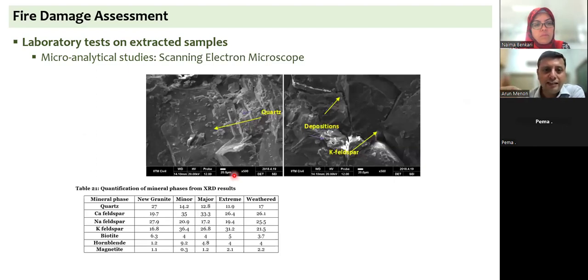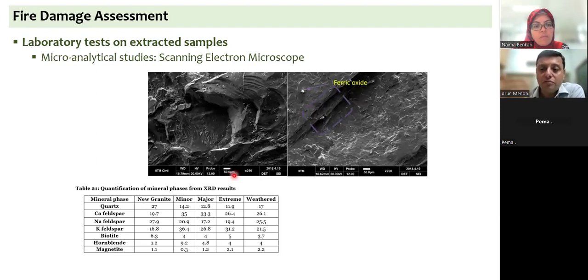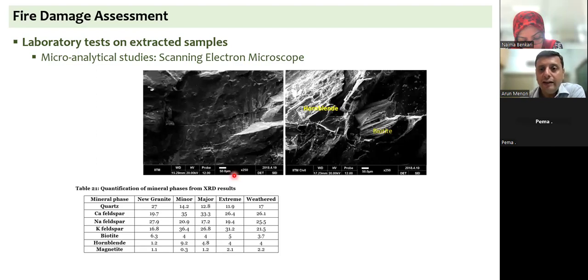What was interesting was to look at these scanning electron microscope images, and in the scanning electron microscope images, we started seeing depositions of ferric oxide, which was an interesting point to be noted, that ferrous oxide is what you have in granite as the mineral, but the conversion of ferrous oxide to ferric oxide by oxidation in the presence of fire was actually happening, and that happens at about 600 degrees centigrade. So there was evidence of presence of ferric oxide in many of these samples, which gave us the evidence of many locations which were from moderate to extreme damage conditions of having reached at least 600 degrees or higher. And that was important to understand which were the more affected columns and which were the less affected columns, and few mineral forms that were typically seen because of this enlargement of the quartz as well.